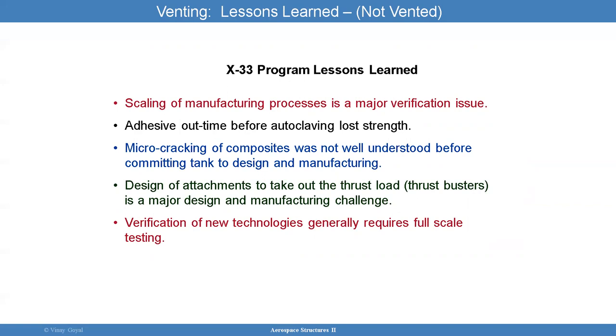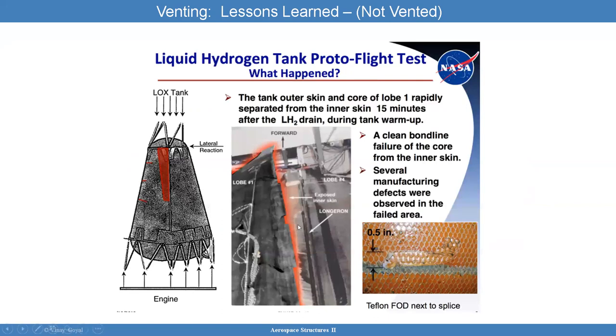The lesson learned from that program is that you have to check the scaling of manufacturing processes to make sure processes at the small scale level can translate to a bigger scale. If the adhesive out time was exceeded, you may want to look at that because that also implies loss of strength. Micro cracking can be an issue for tanks and composites, and venting issues can be a concern that should be addressed and looked at carefully.